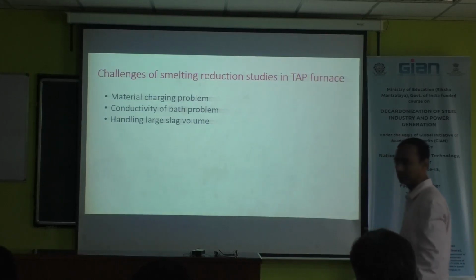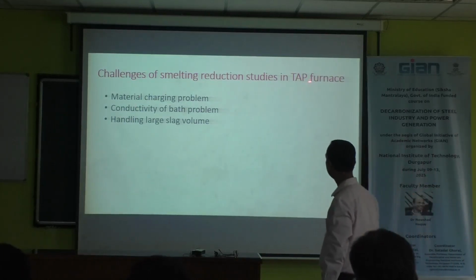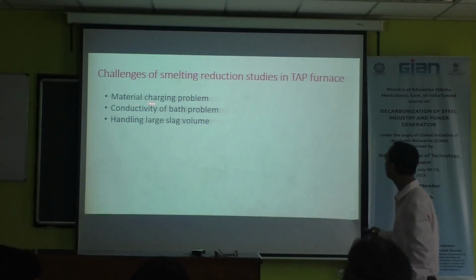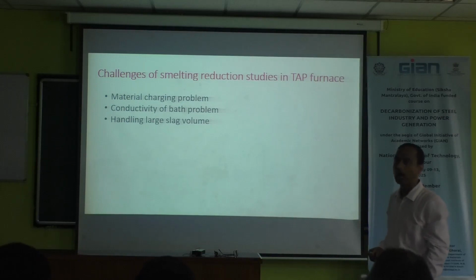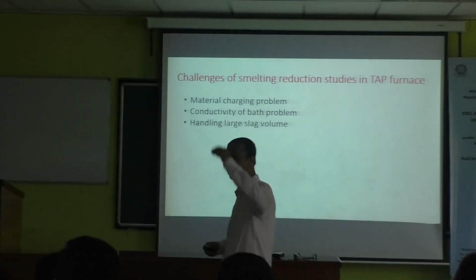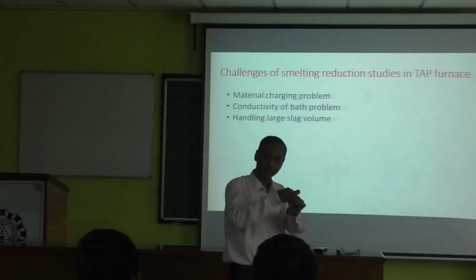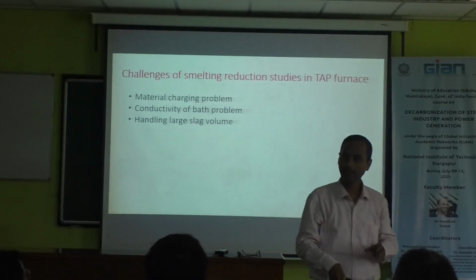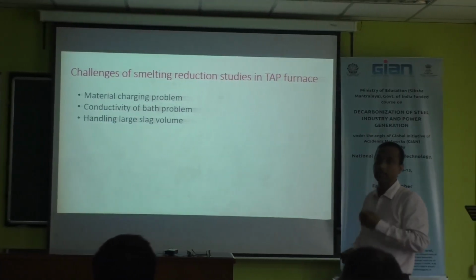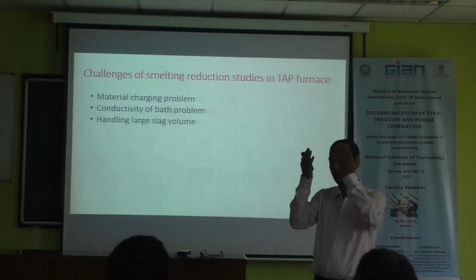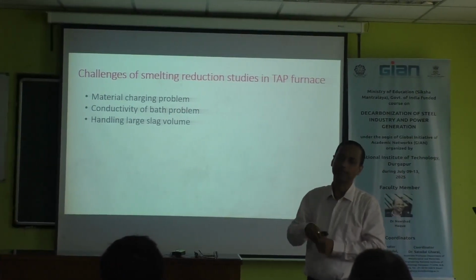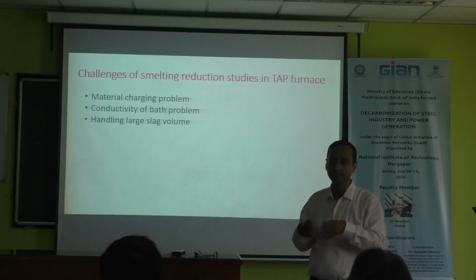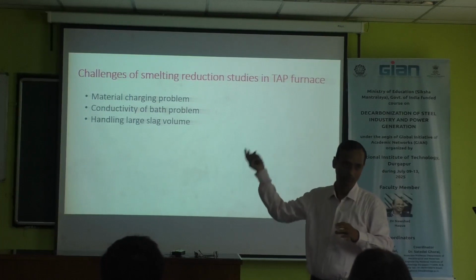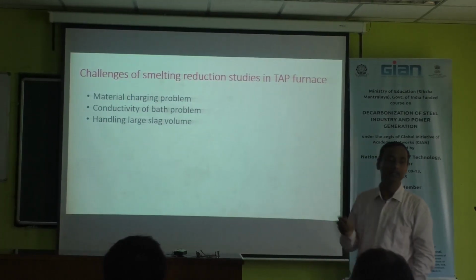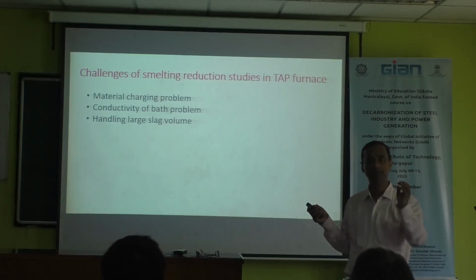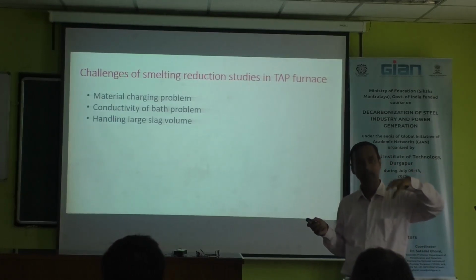So, just the last slide. What are the challenges of smelting the steel? I have discussed all of this. One is the material charging. How to charge? There are two types of charging. One is in-flight plasma, meaning through the nozzle tube, you can directly charge. Because in plasma there is arc pressure and also gas pressure, a lot of fines will come out from the system and go to the ESP. Therefore, we have tested the effect of pellets. If we prepare pellets, there will be less emission.